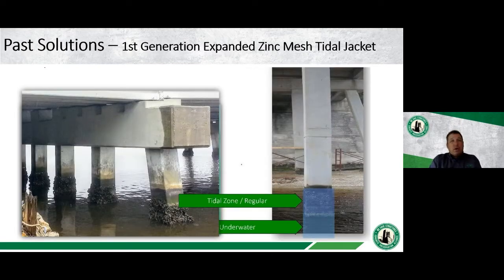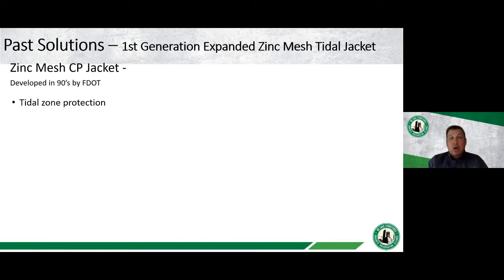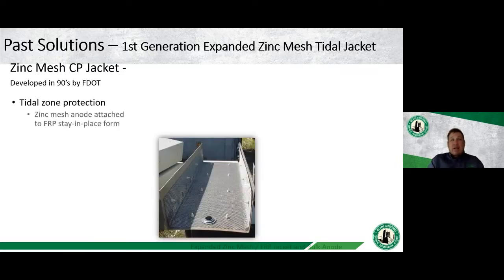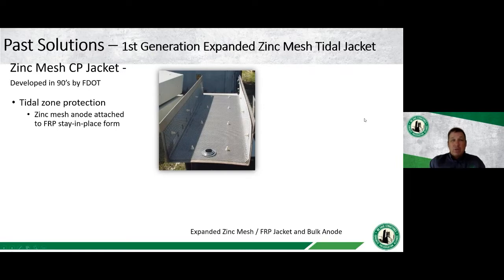So this brings me into one of the other past solutions that was more of a cathodic protection solution. This is going to be just for this underwater area and for the tidal zone, that area where you have that regular tide flow up and down. This was an expanded zinc mesh cathodic protection jacket that was developed in the 90s by the Florida DOT. It was designed for that tidal zone protection. What it consisted of was a zinc mesh anode placed inside of a jacket, and a fiberglass form is also used in this type of jacket system.